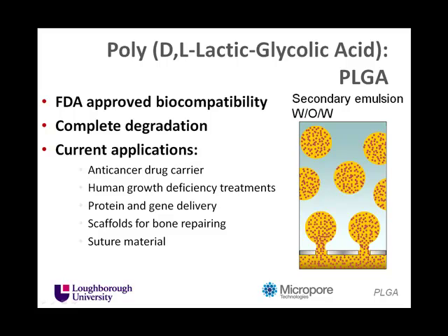So if you want a needle that isn't going to cause too much pain when these particles are being injected, then clearly you want small particles. So it's this balance between small particles which have ease of injection but big enough to have a significant enough payload, and around about 60 microns diameter is the sort of optimum size between those two.